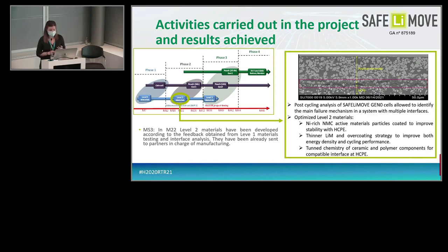And these materials include a nickel-rich NMC, as we were using in the level 1 material, but in this case, a pre-coating strategy has been applied to these particles in order to improve the compatibility with the hybrid electrolyte. Then the lithium metal thickness has been decreased in order, as I was mentioning before, to reach the target of energy density, but also different coating strategies are being tested. And then finally, the chemistry of the hybrid electrolyte has been tuned thanks to the feedback that we reached from the evaluation of the interface between the inorganic and the polymer, and this has allowed us to obtain a more stable and compatible system.